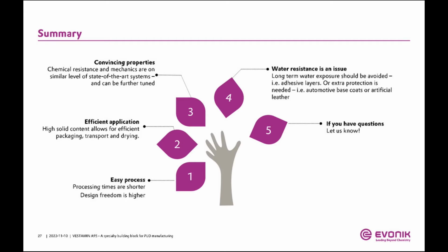We have to admit that the water resistance, this is an issue. So long-term water exposure, I mean, this is, I would say, common to all PUDs if they're not further cross-linked, right? So hydrophilic PUDs are usually not very stable to water, but in this case, the stability towards water is even less. So that means the long-term water exposure should be avoided.